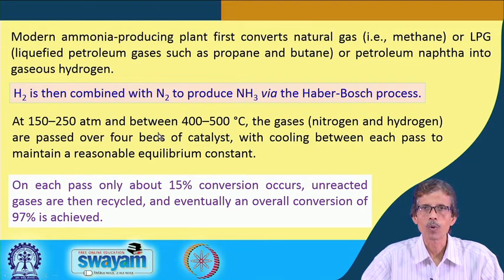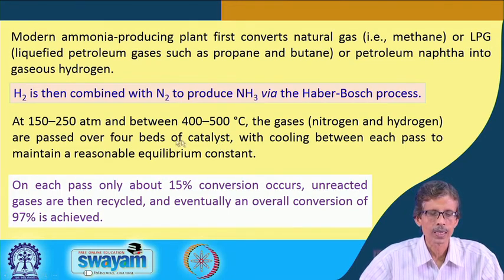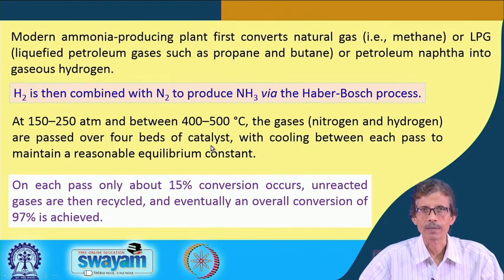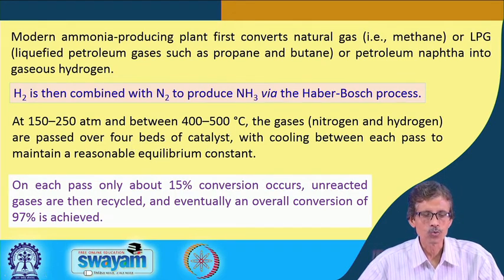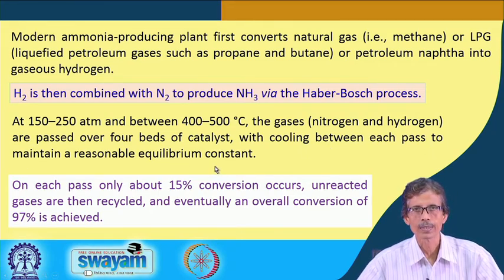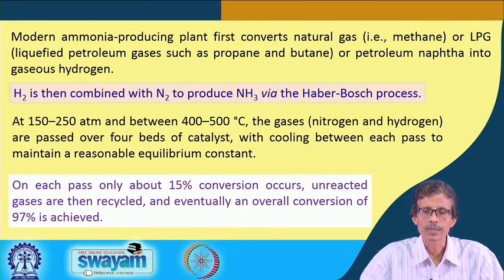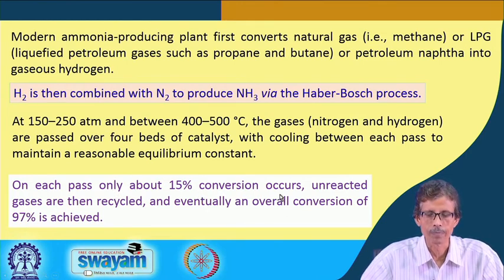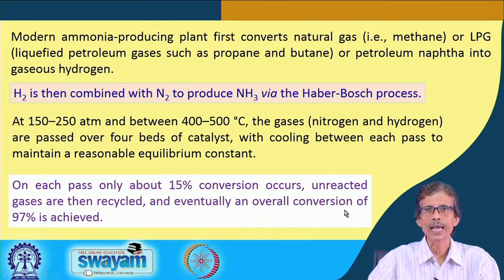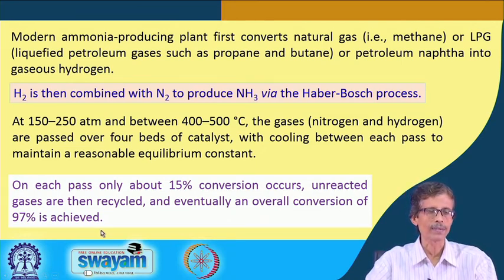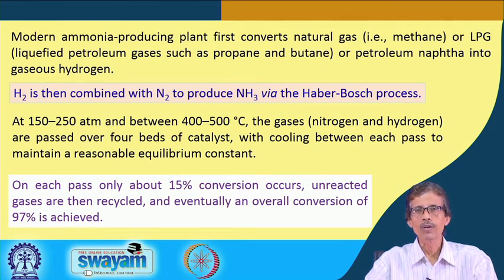But here we use more drastic conditions to achieve that conversion, where we can have four beds of catalysts. Catalysts are very useful for the conversion of these gaseous reactants, with cooling between each pass to maintain a reasonable equilibrium constant, such that the equilibrium constant is favorable and a large amount of ammonia can be produced and the conversion rate is very high. But in some cases, in each pass only about 15% conversion can be achieved, and the unreacted nitrogen and hydrogen gases can be recycled. So, a mechanism for recycling should also be there for the industrial production of ammonia.